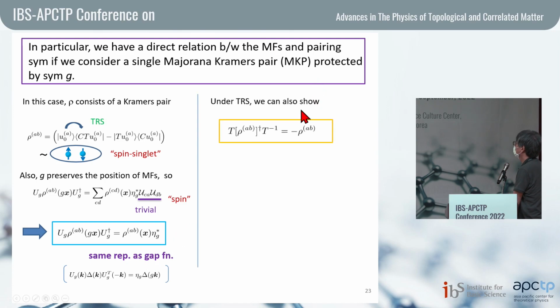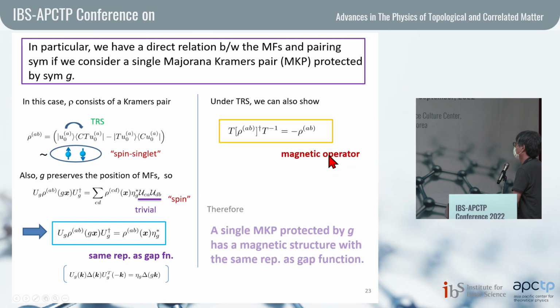And we also found that under the time reversal symmetry, we also have these relations, and actually we have an additional minus sign here. So this means that the rho operator is actually a magnetic operator. So we can conclude that the single Majorana Kramers pair protected by G has a magnetic structure with the same representation as the gap functions. So by using this information, we can determine the magnetic response of the spin-full Majorana fermions.